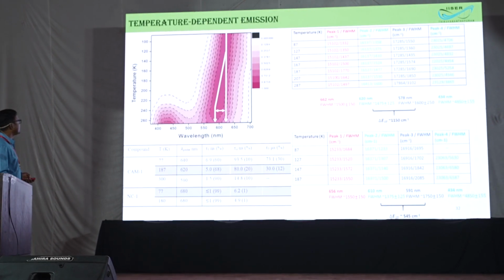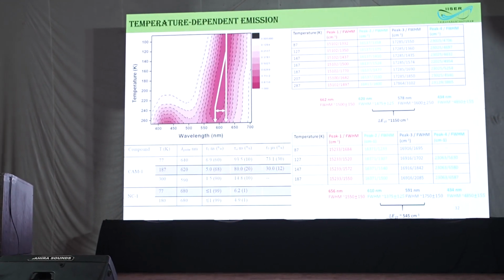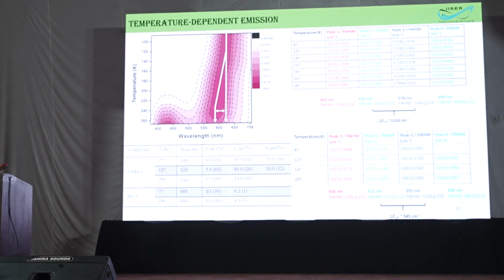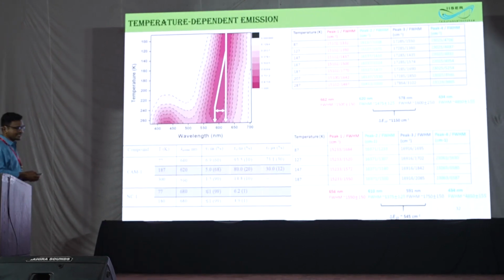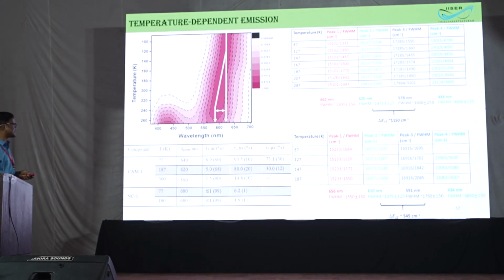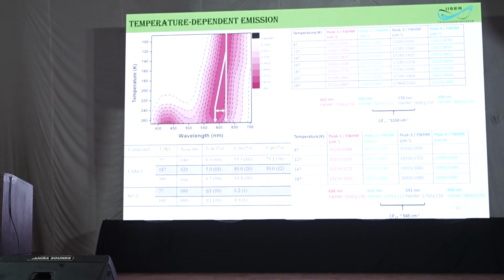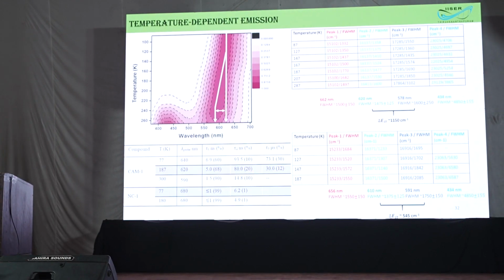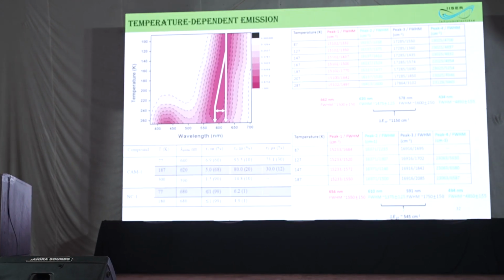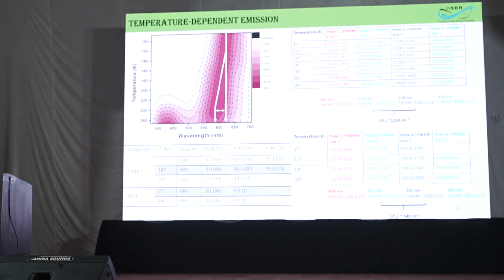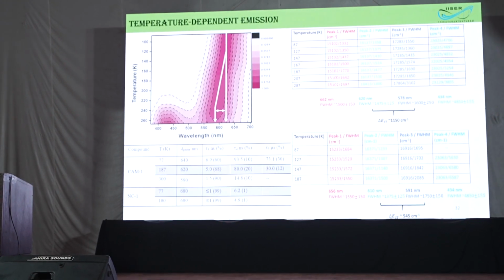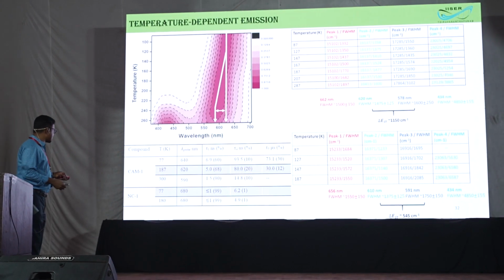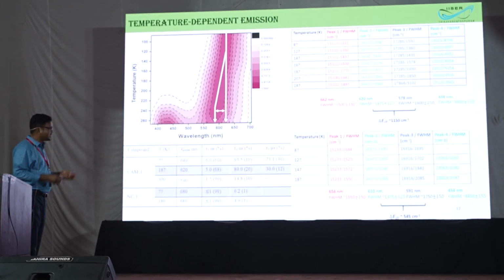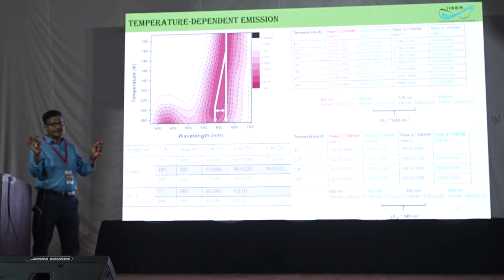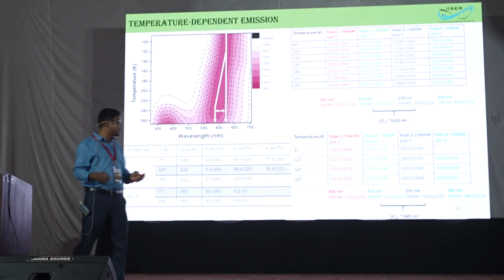In the temperature dependent study, we can see there is a transition at a particular temperature: for 0D around 167 K and for 2D at 187 K. We calculated the Huang-Rhys factor maxima, which for the two-dimensional cluster is 1150 and for the molecular cluster is 545. Then we measured the lifetime, and for each component the lifetime is increased for the cluster-assembled material compared to the molecular cluster. Do remember that the molecular cluster is not emissive at room temperature, but the 2D cluster is emissive at room temperature.